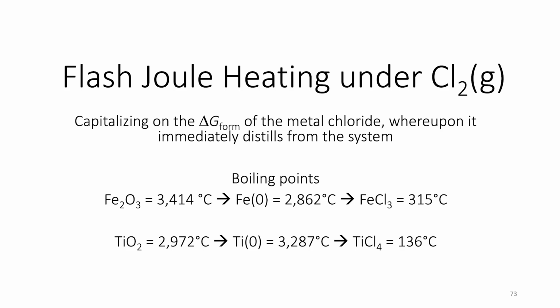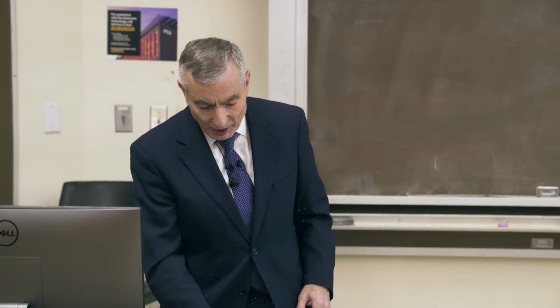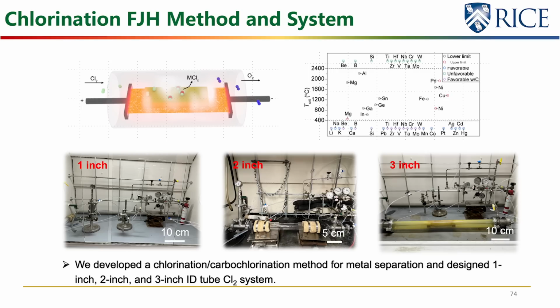Titanium chloride, 136. And so what you want to do is convert these to the chlorides. So what we do is this. We built these reactors. We built a 1-inch tube, a 2-inch tube, then a 3-inch tube. And what we do is we convert them to the chlorides. We flash them under a chlorine environment, and we look at the free energy of formation of the metal chloride. And we capitalize on that. As soon as we form the chloride, it distills out.